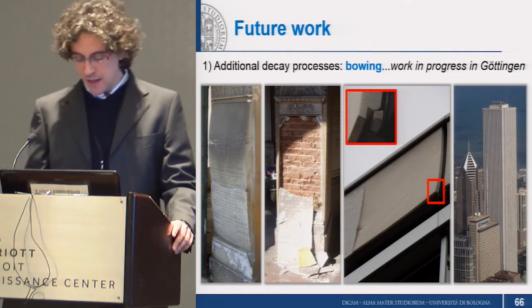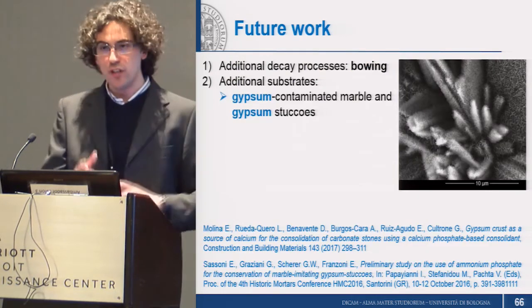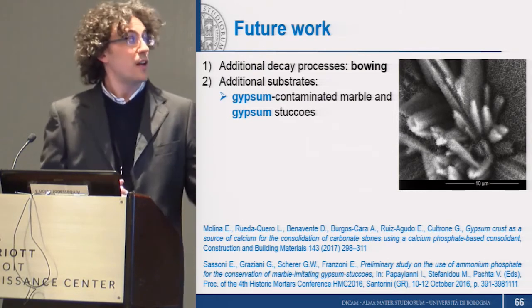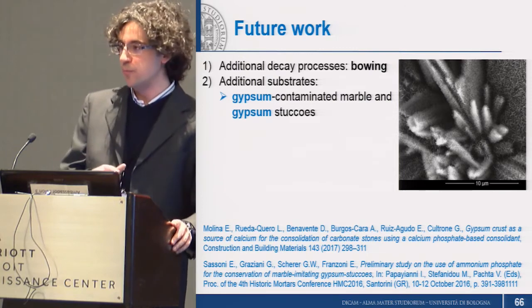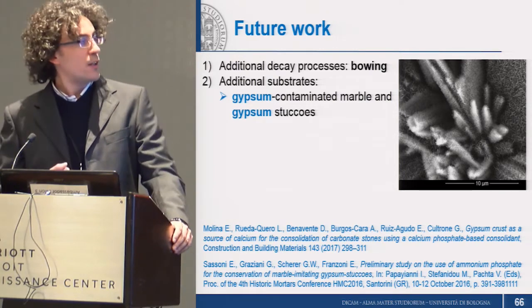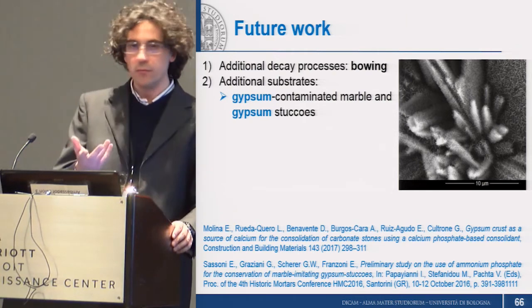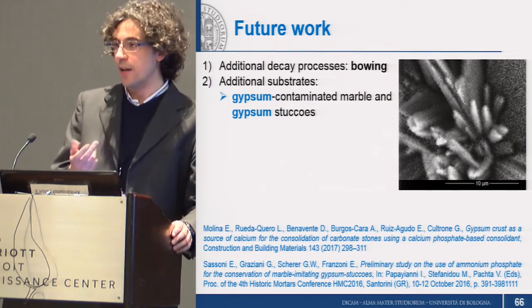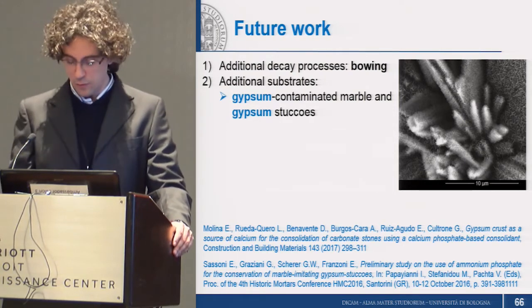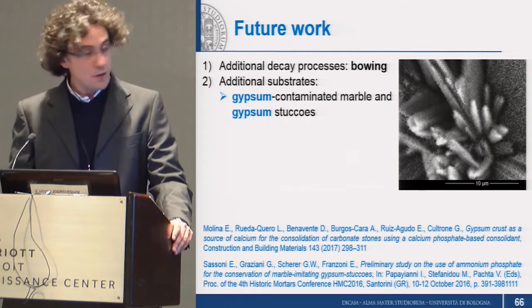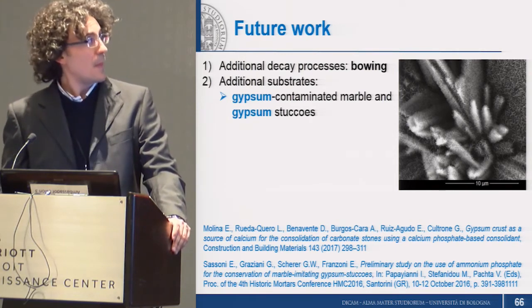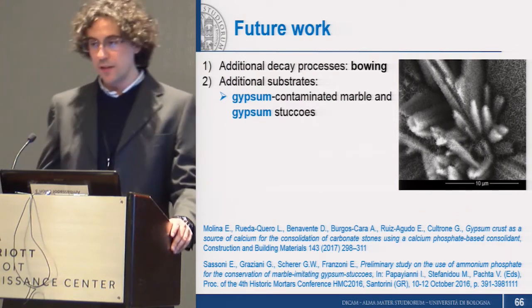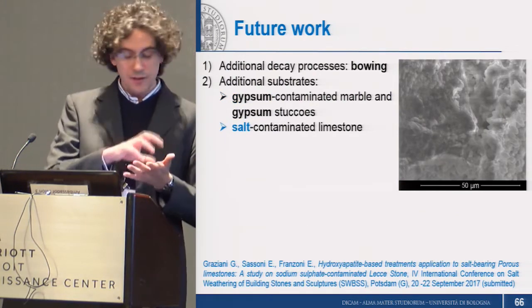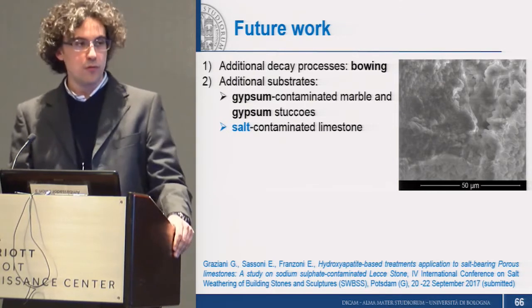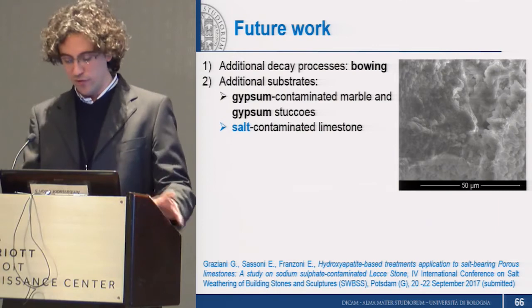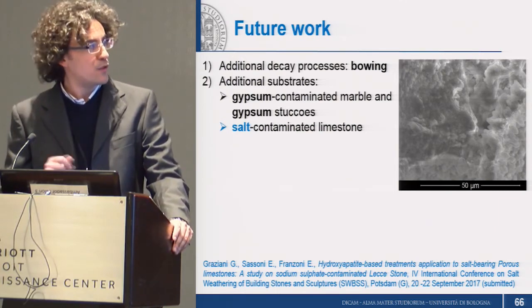Then the community is also now investigating the effects of this hydroxyapatite treatment on a variety of substrates, starting from gypsum-contaminated marble, but also gypsum stuccos. And this is an important aspect because, as you well know, gypsum is more soluble than calcite, so more calcium ions are available for the reaction. So the treatment needs to be tailored for this specific substrate. Similarly, we are also investigating the effects of applying the treatment to limestone that contains salts inside the pores, which is usually the situation because even if salts are removed before the consolidation, a complete removal is mostly impossible.